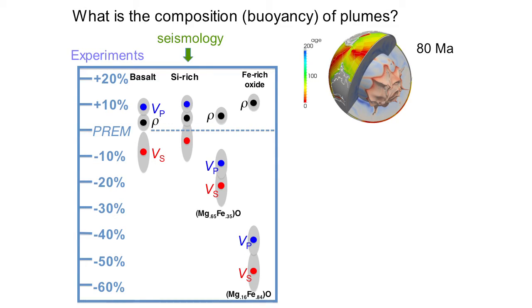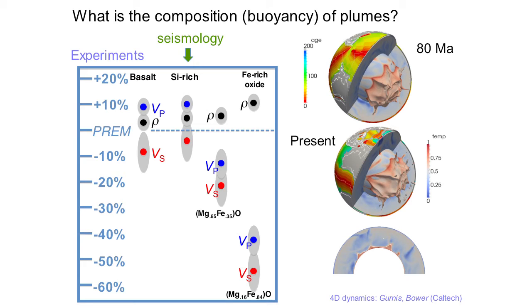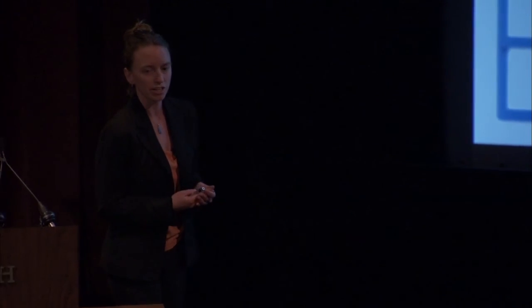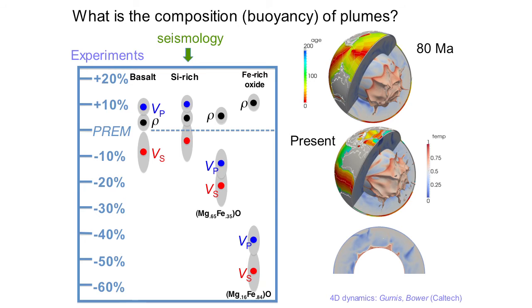which we show here as a 4D model tracking plate tectonics over 200 million years and taking snapshots at 80 million years to the present. And this is a structure underneath the Southern Pacific, which is evolving over time, which takes into consideration these density anomalies associated with the composition that we inferred seismically and from the experiments. So this can help us aid in the link between buoyant material from the core-mantle boundary and perhaps the long-term evolution of this volume and whether or not it will eventually rise up to the surface.